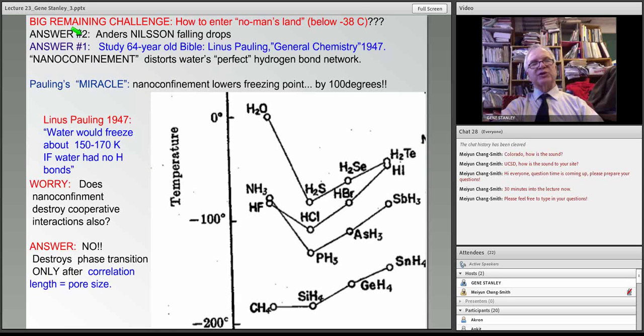And there's two answers to that. One, many of you know about it, that Anders Nilsson, one of the best experimentalists working on water, is making measurements at SLAC on falling droplets of water. And because they fall into a chamber where the temperature is below the homogeneous nucleation temperature, this means that for a short period of time, they don't freeze. They don't freeze because they're very tiny, and to freeze you need nucleation. So if you let fall a lot of drops, a goodly number of them won't have any nucleation sites, and it will stay liquid. And during this tiny bit of time, while they're falling, you can make measurements, and that's what Nilsson did.